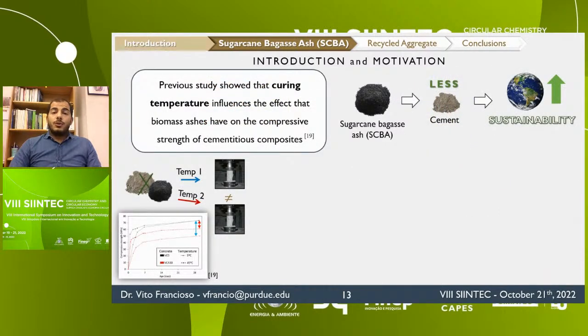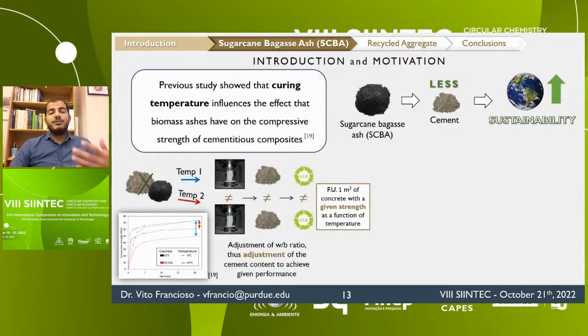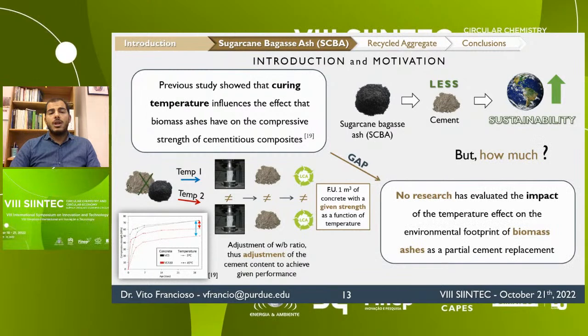Previous studies show that curing temperature influences the effect that biomass ashes have on compressive strength of cementitious composites. If the temperature changes the effect of these ashes on strength, the cement content needed to achieve a given performance will also change. Then, what are the real savings of using bagasse ash, of biomass ash, in terms of cement reduction as a function of the curing temperature, right? We need to compare the samples with the same performance to make a fair comparison. So we realized that no studies evaluated before the effect of the curing temperature on the environmental footprint of using bagasse ashes in cementitious composites.